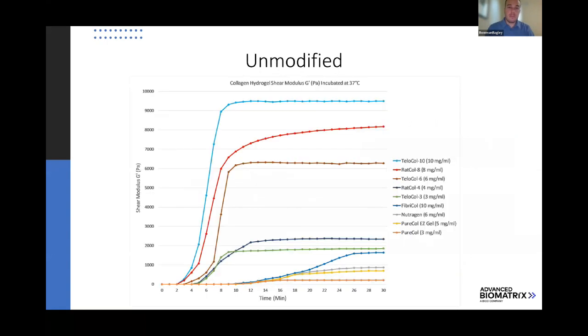And so initially the first answer that we had was, okay, our collagen materials. So this is a graph where we're looking at the 3D gelation of our collagen hydrogels at 37 Celsius over time. And then you're looking at the strength of the gels. You'll see the telocollagen gels are the ones that gel very quickly and form stronger gels. The atelocollagens gel much slower and much softer.